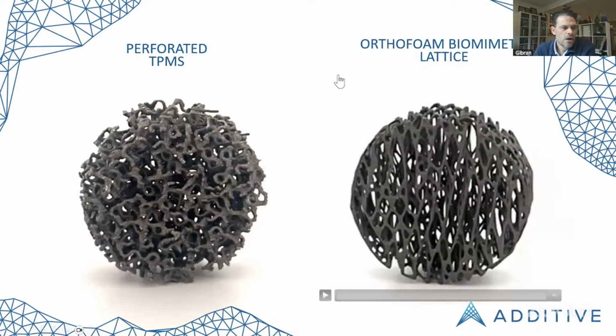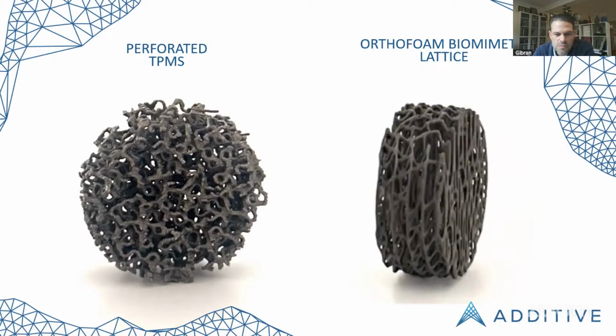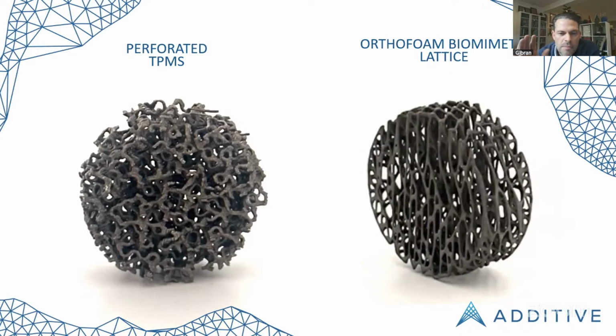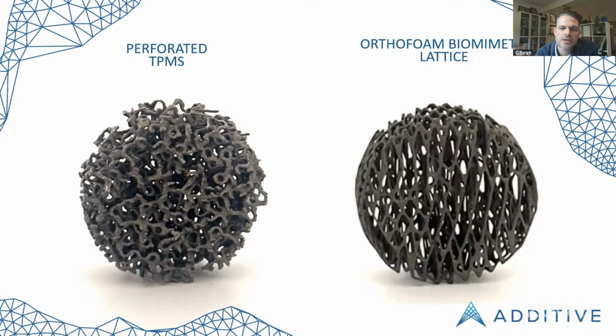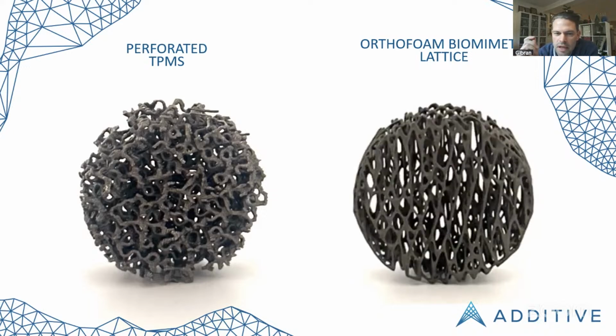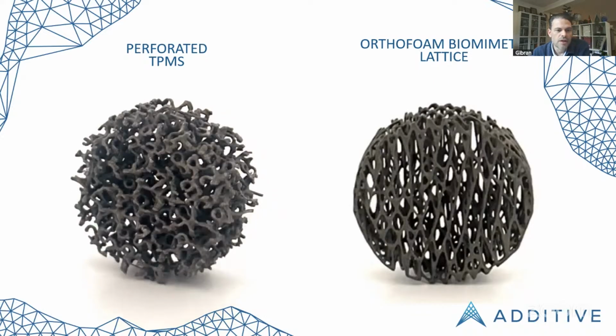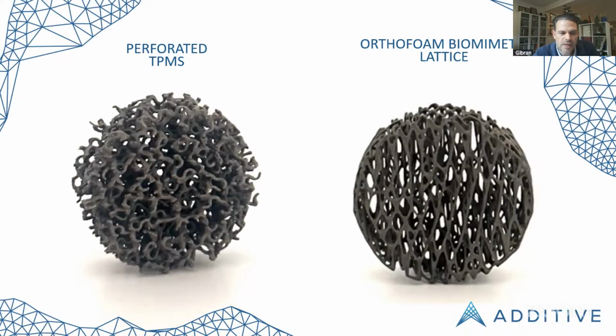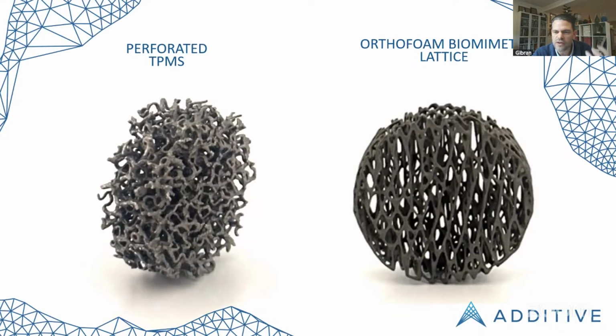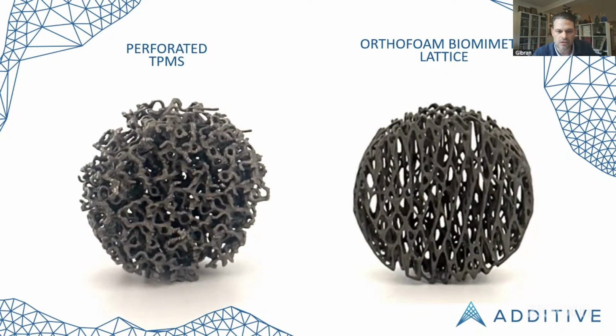When you put these two lattices together, you've basically got, I'll show you here. So again, we can see these two lattices. On the right-hand side, we've got the orthofoam biomimetic lattice. And when that's spinning around, you can see the open pore structure. You can see right through it. The light just comes right through it. And that's exactly what we wanted. An irregular, organic biomimetic lattice that will encourage strong bone growth and distribute load evenly. Then on the left, the perforated TPMS is like Velcro for the end plate. So it's very grippy. It'll stick quite well.